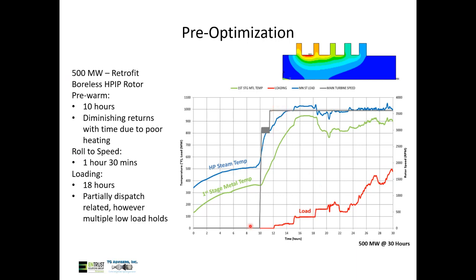Now, the point to think about is that by the time you reach full speed and you have load on the unit, if you were going to have a failure, it would have already occurred earlier in the startup process, when the rotor was cold and brittle and had that high steam to metal mismatch. So we typically don't see a lot of benefit in this extended hold once you get to low loads. Just something to think about, because again, the material properties are so much better at that point. So the rotor can withstand larger stresses, and it's in a good state.